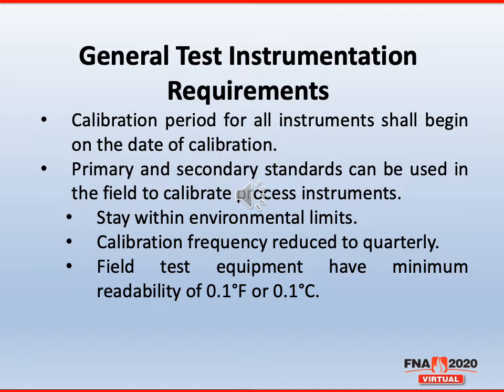We also addressed that primary and secondary standard instruments can now be used in the field to calibrate your process instruments. We do have a couple caveats on that: they must stay within your environmental limits as described by your manufacturer's tolerances. So if your manufacturer's tolerance for a standard instrument says as long as it stays within 105 degrees Fahrenheit and less than 90% humidity, and your shop is in that realm, yes, you can go out and use your standards to calibrate your process instruments.